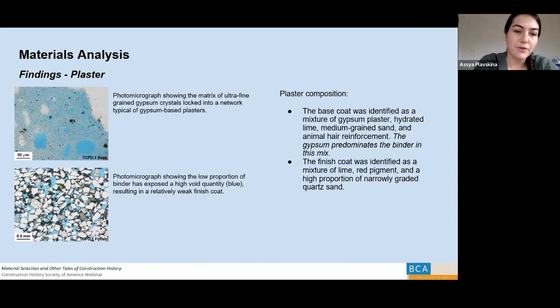We found that the finish coat plaster mix was really highly sanded, which meant there were a lot of these voids, and that caused a crumbly, fine, fragile plaster. And we did unfortunately see that in situ while performing a conditions assessment.